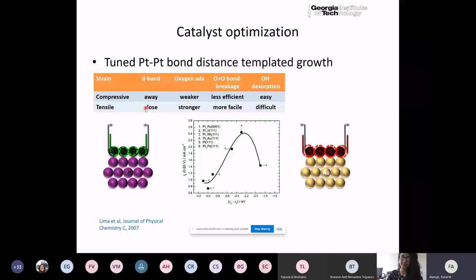So if you look at the effect of these tension or compression, you find that the electronic band, the D band, which is the relevant valence band for the platinum, essentially can move up and down relative to the Fermi energy, and that has consequences on the chemical reaction. So if you put compressive strain, then it moves away, versus if you put a tensile strain, it moves closer to the Fermi level. And when we're saying it moves, we're talking about, let's say, the center of mass of that band. So the effect of that actually is that it affects all parts of the oxygen reduction reaction.